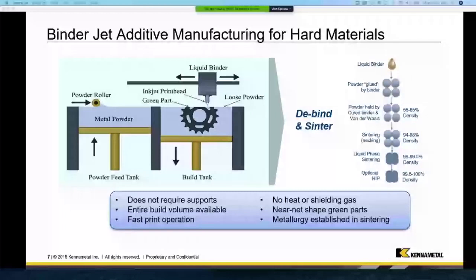Some of the advantages with binder jet technology is the fact that it's the only reliable technology at this point for printing of very hard materials like tungsten carbide. It also does not require that you build any supports in your print bed. You can use the entire volume of the build box and build all the way out to the edges. There's no heat or shield gas required in the printing operation. You do end up with what's considered a green part, just like other powder metallurgy processes, and your final metallurgical properties are established in the sintering furnace, which also creates a flow path that's much more aligned with traditional powder metallurgy.